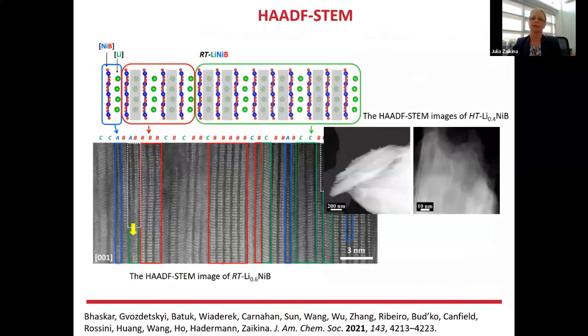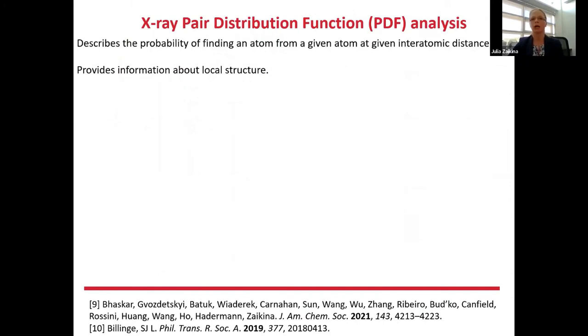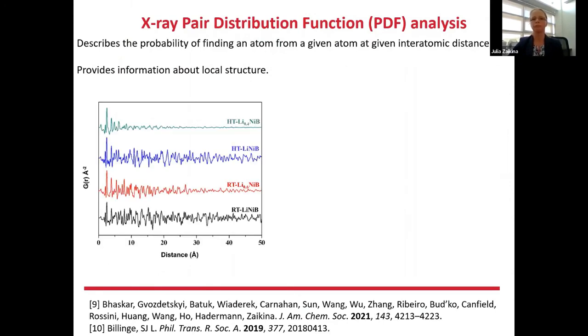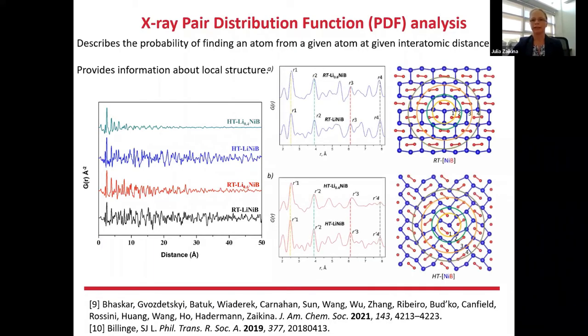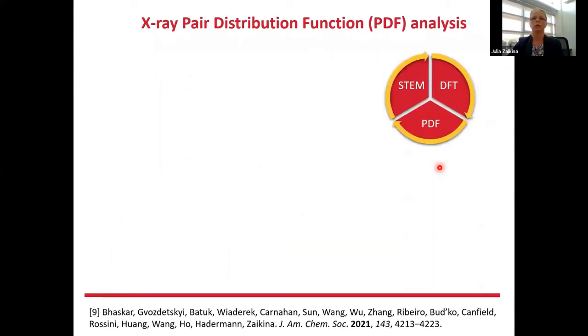So still, scanning transmission electron microscopy didn't give us the precise information about where the atoms are located. So we used X-ray pair distribution function. We collected the data at APS, and we do see that upon the deintercalation, the local structure of the nickel-boron layer doesn't change a lot. So we use 3 methods in synergy. Our initial models came from STEM. Then we optimize them by using DFT calculations and then refine those models further with the X-ray PDF.